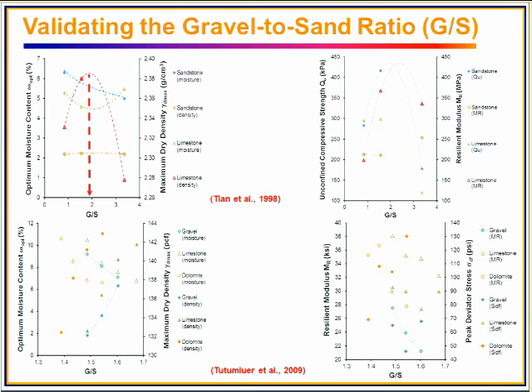And then we collected one database from the University of Oklahoma. I think that was completed in 1998. They studied sandstone and limestone, two different types, with different gradations. So we also use this database. The optimum range we found, for example from the left figure, optimum moisture content and dry density versus GS ratio, is about 2. The value is higher because for MnDOT they used AASHTO T99 standard compaction. For this one they used AASHTO T180, modified compaction. Because the compaction level is higher, maybe the range is higher.